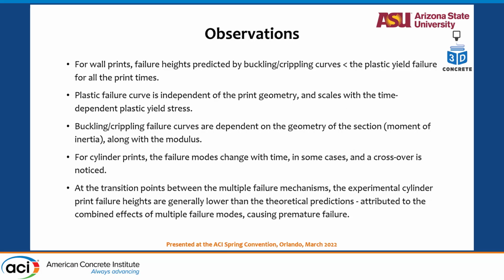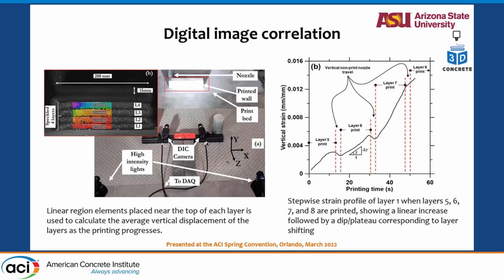But the idea is that using any of these established models and the parameters extracted from a very simple green compressive test, carefully done though, to get the plastic and elastic parameters, you can actually predict the failure heights fairly nicely for the cases that we talked about. Now the question is, okay, I have predicted it, I have 4 more minutes. Good. So I've predicted this.